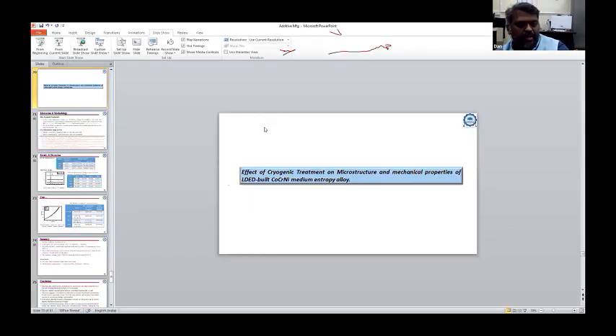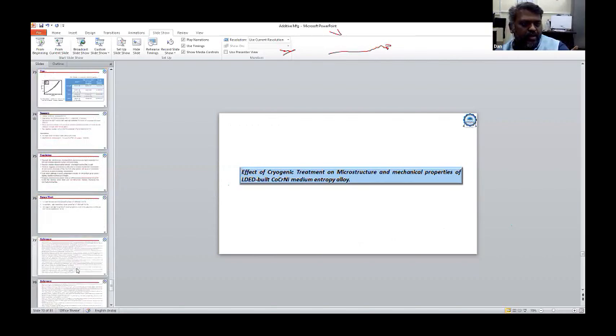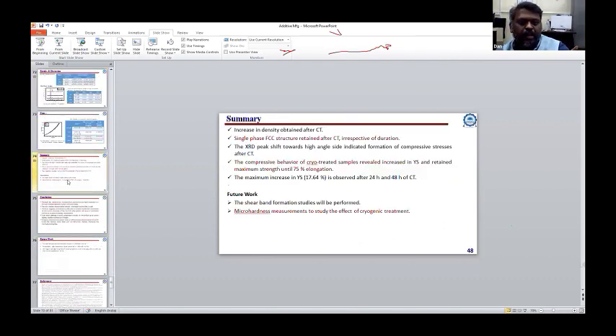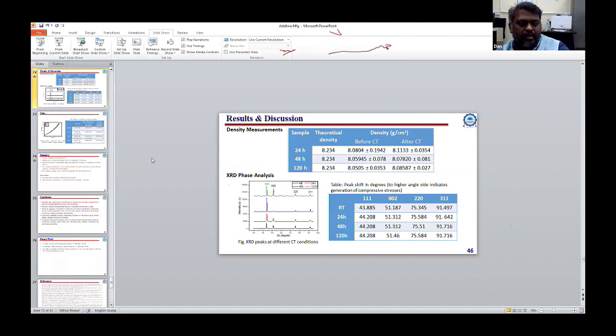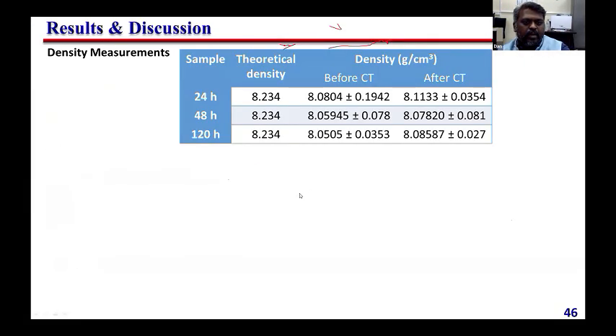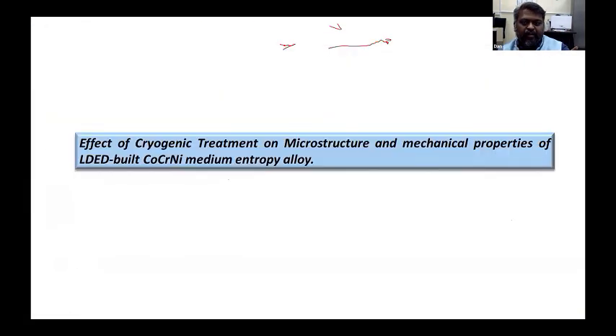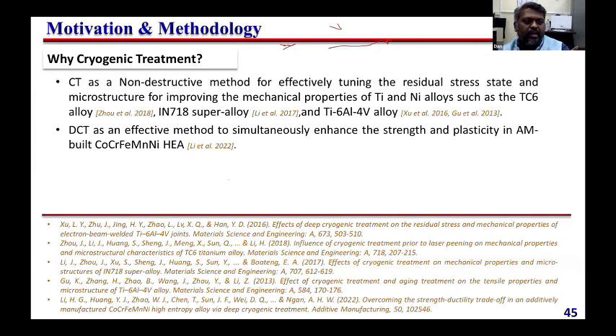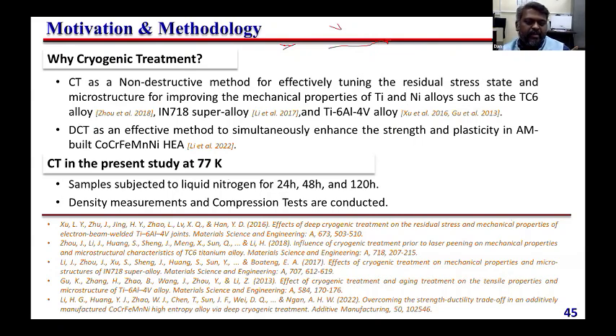Also I can show some kind of post processing technique. We did some kind of cryogenic treatment for different hours on this particular sample. We tried to see if there is any change or not. This also will act as a microstructural refinement.